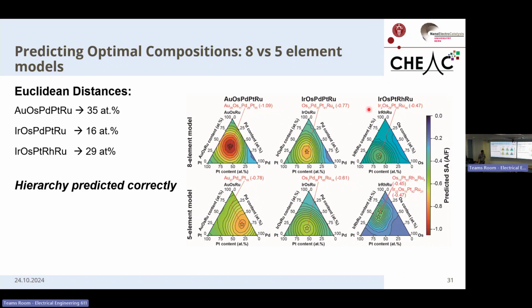So the reason for this discrepancy can be attributed to the undersampling of the 8-element model. So remember, in the initial calculations, we needed to do 950 experiments. Due to time constraints, we limited it to 200 experiments, so we lack a bit of pinpoint accuracy. However, the good thing is that the hierarchy is still predicted correctly. So while the pinpoint accuracy is lacking, the hierarchy that we have is still correct. The gold, osmium, palladium, platinum, ruthenium is the most active subspace of them all. So the map that we have seen previously is still valid.